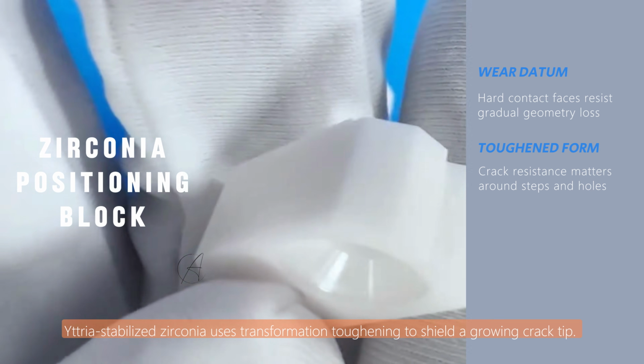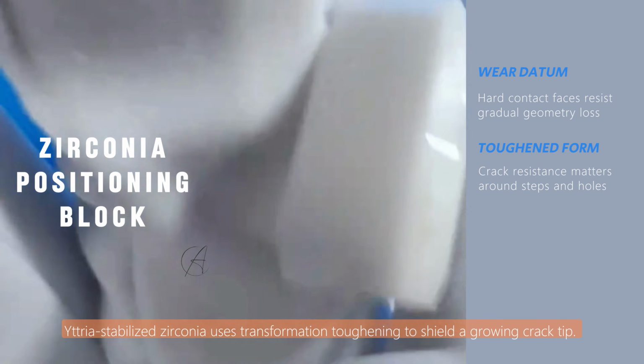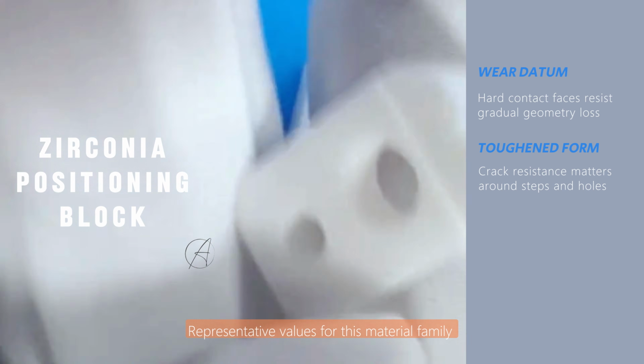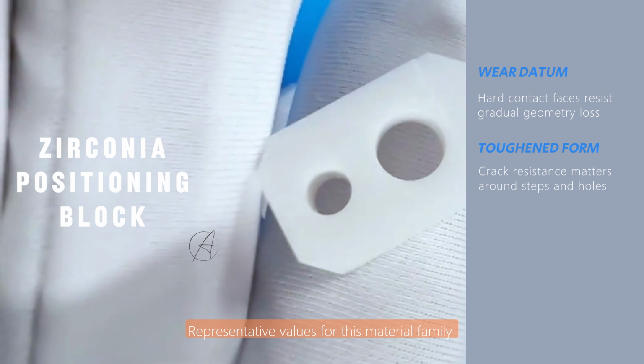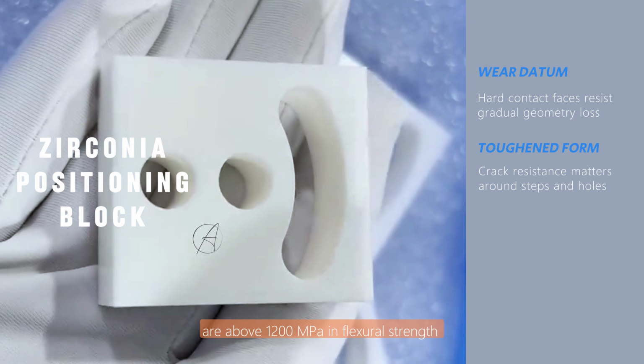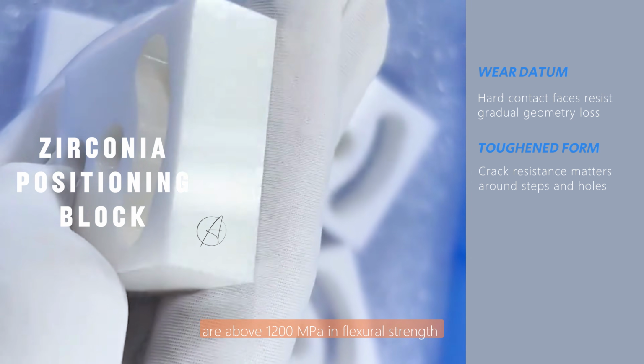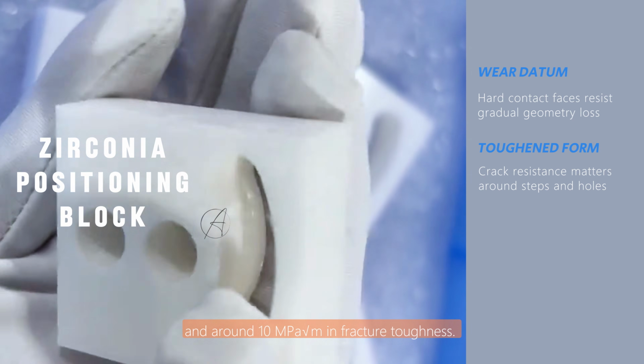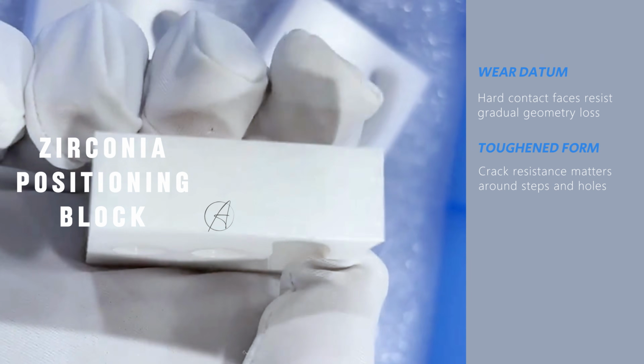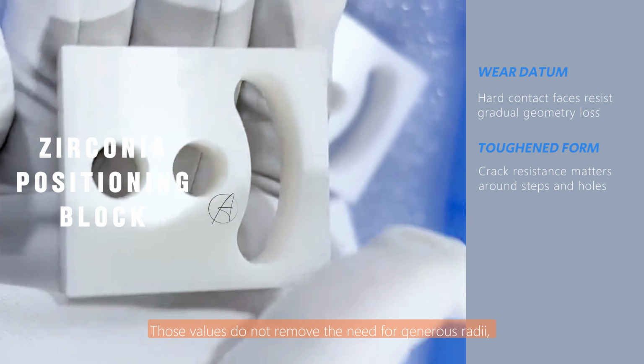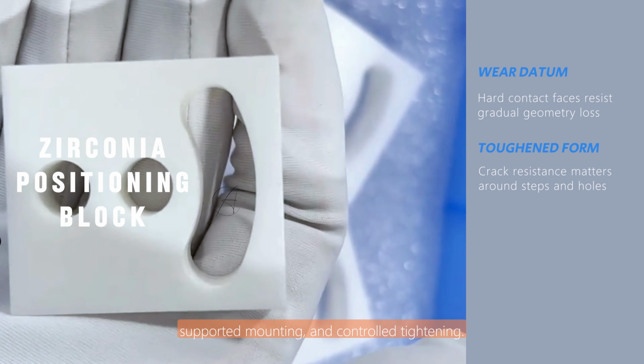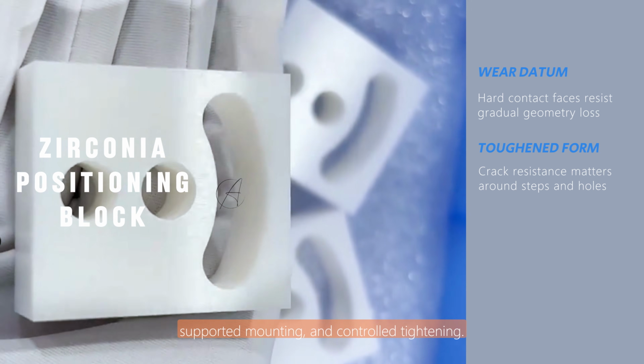Yttria-stabilized zirconia uses transformation toughening to shield a growing crack tip. Representative values for this material family are above 1200 megapascals in flexural strength and around 10 megapascal root meters in fracture toughness. Those values do not remove the need for generous radii, supported mounting, and controlled tightening.